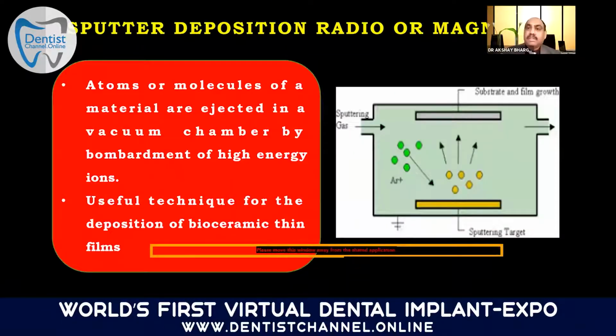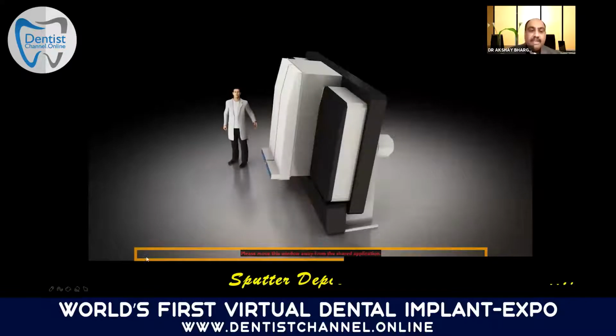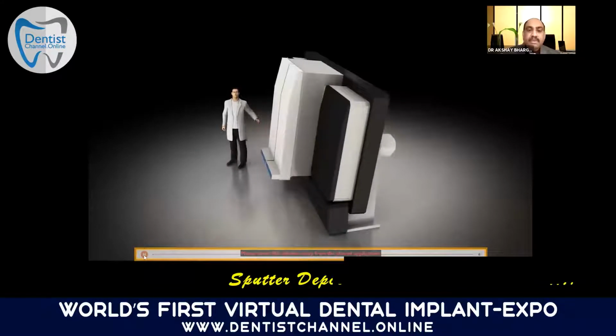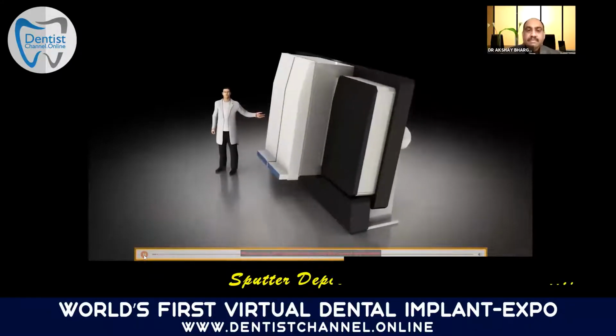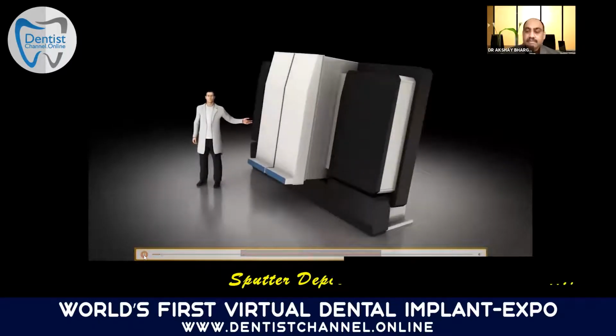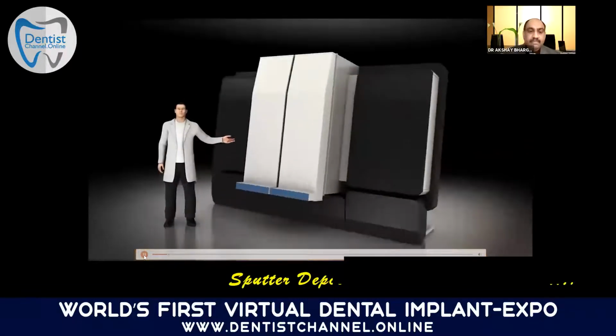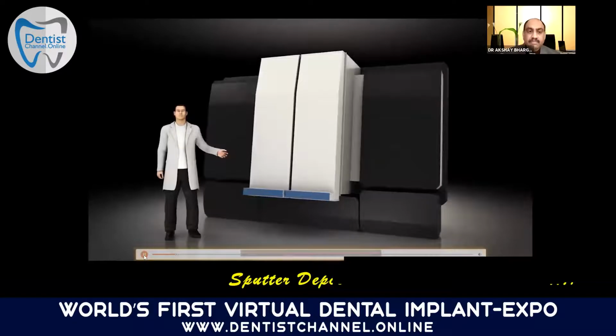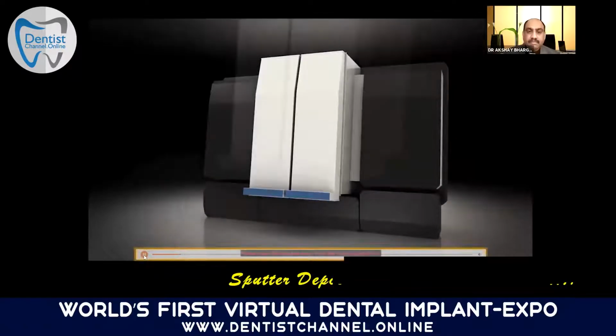The next type of surface treatment is sputter deposition, radio frequency or magnetron, where atoms and molecules of a material are ejected in a vacuum chamber. With sputtering, you have a creation of a rough surface. Again, a small video to show you. Sputtering deposition is done in a vacuum chamber. The most common substrate for the thin layers is glass. The sputter system can have different sizes depending on the application.